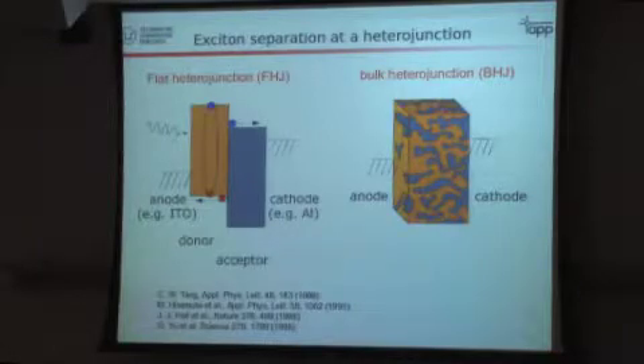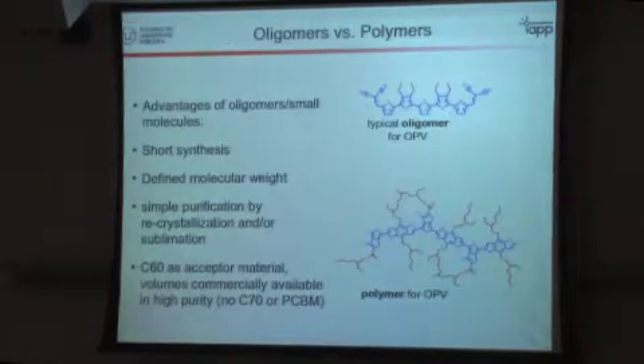So at the end, what we do have is a nanomorphology of domains of a donor and an acceptor material. The energetics must be okay. The transport in this morphology must be okay. The orientation of the molecule must be controlled. And this altogether is a very difficult and challenging issue, as I'll show you in some detail. Now, when we come to organic PV, there are kind of two schools.